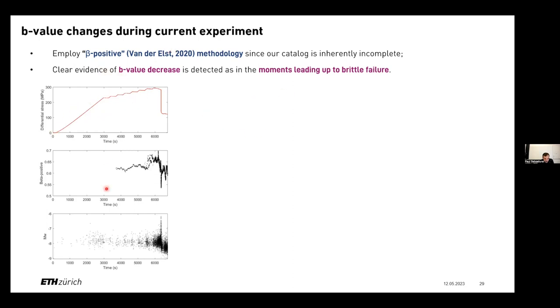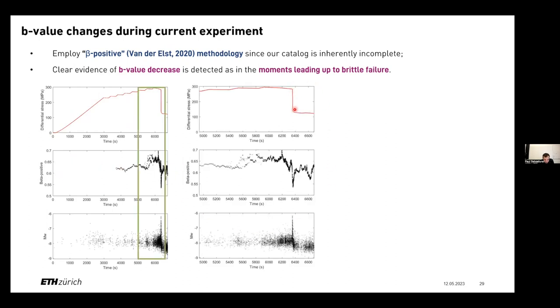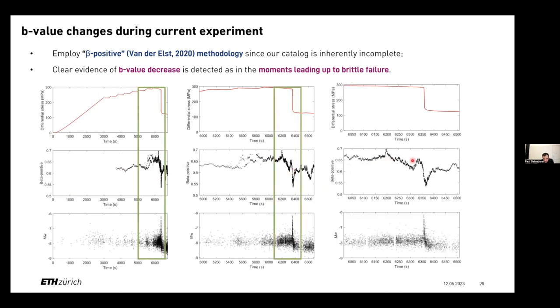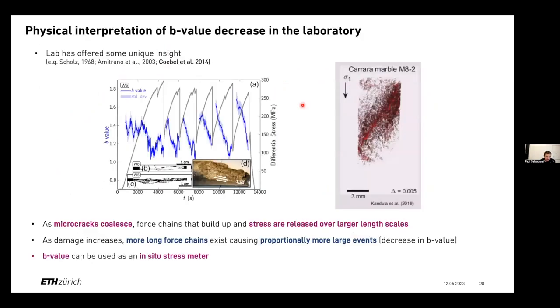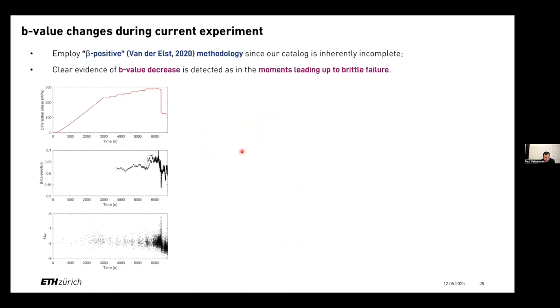And what we do is we see clear evidence. This is the experiment I just showed you and the beta positives here. When I zoom in closer to the big stress drop, this is the macroscopic failure. We start to see that, yes, there is this drop leading up to the major stress drop. What you can notice here in the latter stages, when the beta positive value starts to drop, the differential stress is relatively constant in this case. There is a general decrease, but there are some fluctuations in the B values that we don't understand.